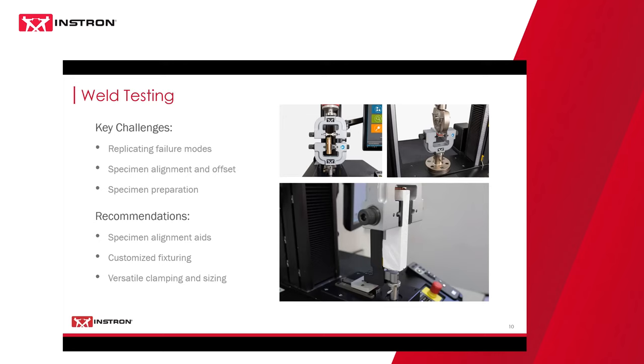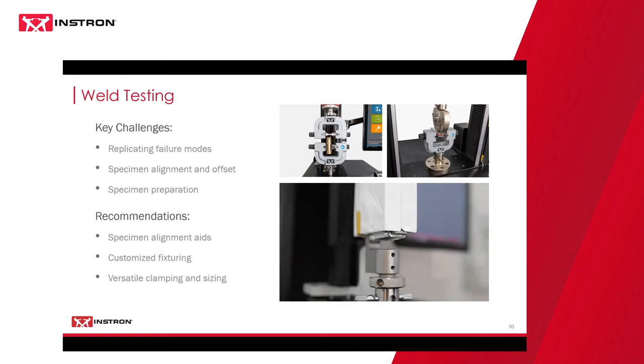So you want to make sure you have alignment from one specimen to another, one operator to another, again, coming back to that. An example of fixturing that Instron's worked on is for a prismatic cell, for the current collector on a prismatic cell, shown in the bottom right here. I'll play the video in a second. This fixture has an alignment aid that comes into place and helps with the insertion of the specimen, and then can move out of the way when you begin your test. It also has a lower hook that ensures proper alignment and the proper failure mode of this test. So you see moving the alignment aid out of the way. I'll show you a close-up of the lower hook there.